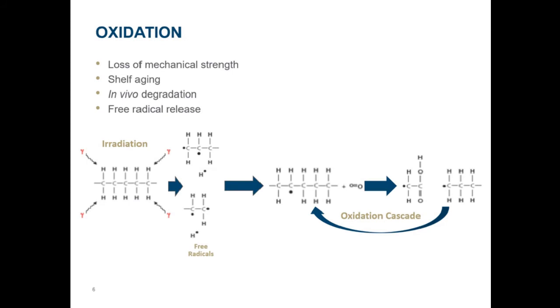When polyethylene is irradiated, polymer chains are broken and free radicals are generated. When these free radicals are exposed to oxygen, a cascade reaction occurs in which the polymer chain is further degraded and more free radicals are generated. Gamma irradiation of polyethylene generates free radicals within the material which can react with oxygen and lead to reduction of mechanical properties, thus oxidation.